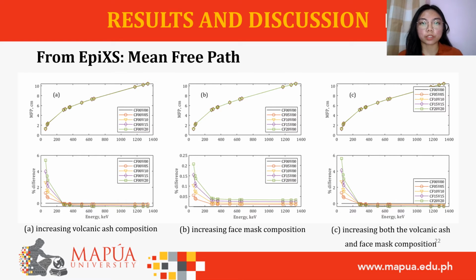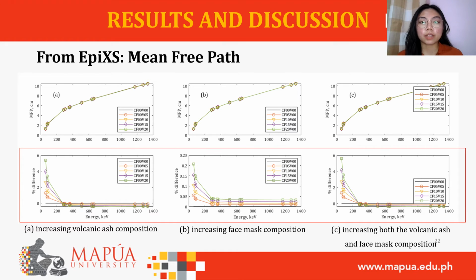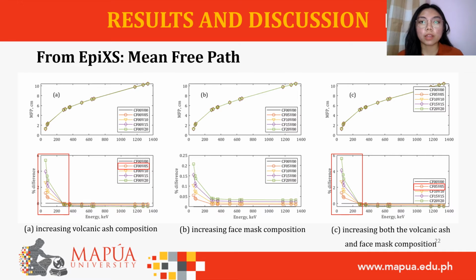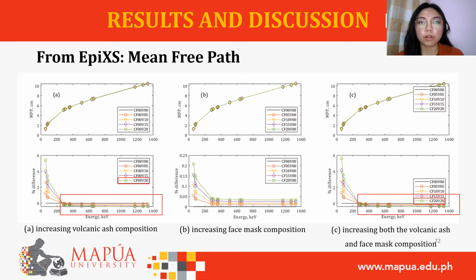For the MFP, a low value is more desired since it denotes the average distance traveled by a photon before its first interaction. The MFP of the samples in all cases has a small percent deviation from the reference concrete CF00V00, shown at the second row of the graphs. Also, similar to MAC, the MFP values of samples CF00V05 and CF05V05 are more advantageous below 300 keV, while the samples CF00V20 and CF20V20 are more advantageous beyond 300 keV. Since the volcanic ash contributes more to the concrete mix than the face mask, increasing both their compositions up to 0.20% face mask and 20% volcanic ash showed an advantage in the high energy region.